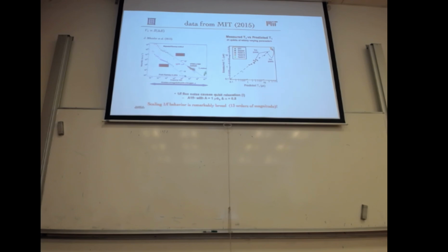And basically, so we are at the level of 5 to 10 gigahertz. And basically what they were seeing, as I told you yesterday, is that when we look at the relaxation of the qubit, what we are probing is the noise power spectrum of the environment at the same frequency of the qubit. And then they looked at this T1 for different kinds of qubits. And what they saw is that the value of this T1, this gamma 1, is very nicely given if you assume it is an extrapolation of this 1/f noise, and when you look at the amplitude, it is the same amplitude of the 1/f noise that you have at low frequency.